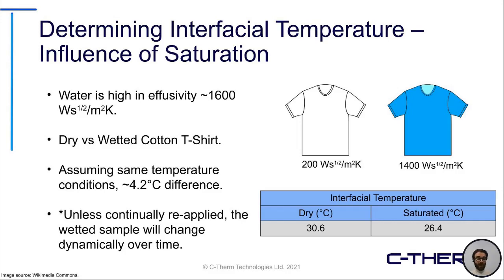Using the example of a wetted sample. Water is very high in effusivity, approximately 1600 Ws^1/2/m^2K. So you could do just the direct measurement of a dry versus a wetted cotton t-shirt, let's say. The dry cotton t-shirt coming in at, let's say, 200, compared to the wetted cotton, which would be much higher. You obviously know that the wetted material feels cooler based on the fact that it has a higher thermal effusivity, but you can actually quantify how much cooler that would feel by using these calculations. You can see that you're getting about a 4.2 perceived degree temperature difference between the wetted and dried state.